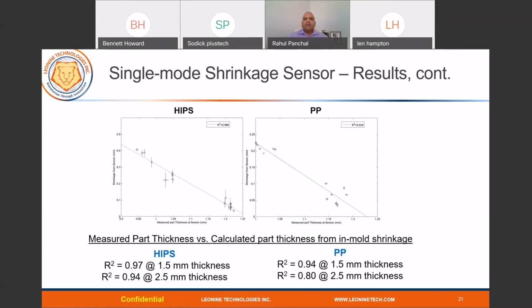So now we calculated the part dimensions, measured the part dimensions at the same location as the shrinkage, and if you correlate them, it's almost 97% correlation for HIPS, 95% correlation for HIPS at the thicker cavity, and 94% correlation for polypropylene at the thinner cavity, and around 80% at the thicker cavity.